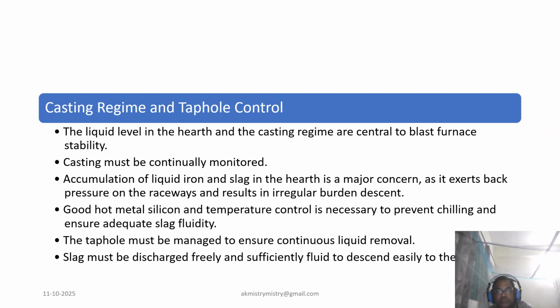Continuous monitoring shows that the hot metal silicon content often provides an earlier indication of a cooling trend than hot metal temperature itself. Finally, even basic steps like taphole drilling should be maintained via automated control to ensure consistency.